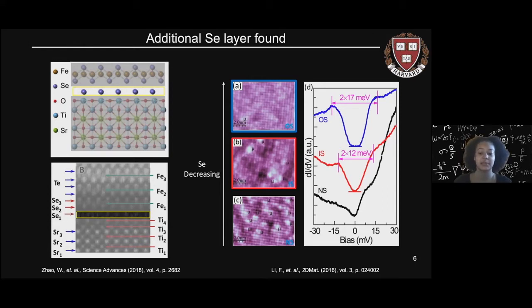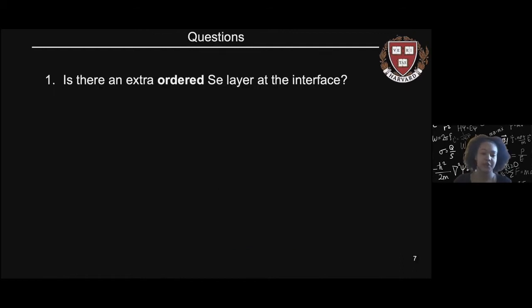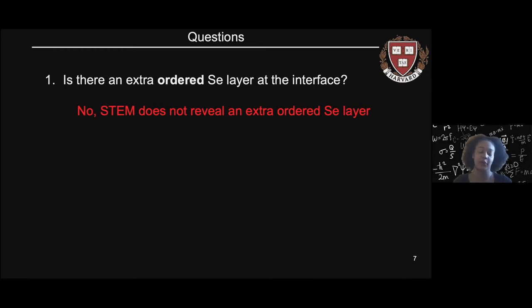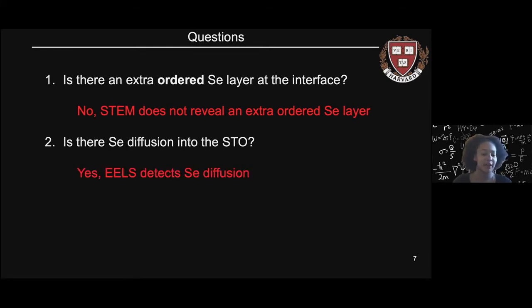So these studies provided motivation for our study, which led to two specific questions. First, is there an extra ordered selenium layer at the interface? And I'll present our findings to you today, which conclude no, our STEM images do not reveal an extra ordered layer of selenium. However, we then dig deeper and ask, is there selenium diffusion in the strontium titanate bulk? And our electron energy loss spectroscopy, or EELS measurements for short, do detect selenium diffusion. So these are the two results I'll be presenting today.